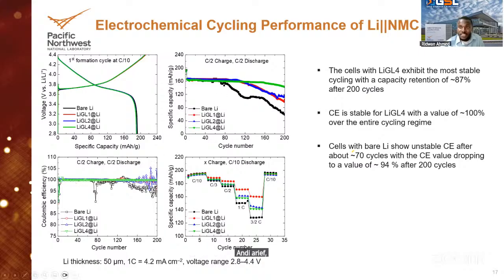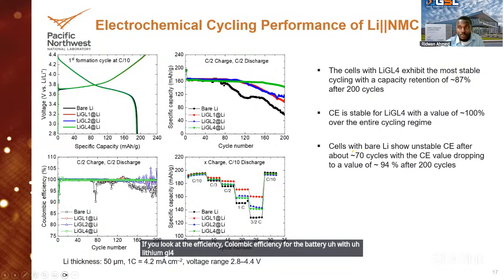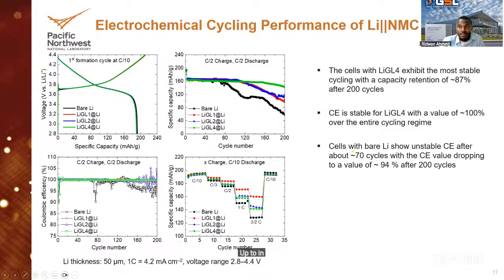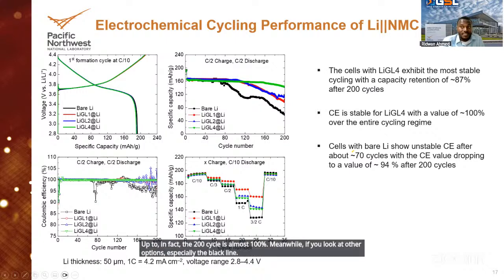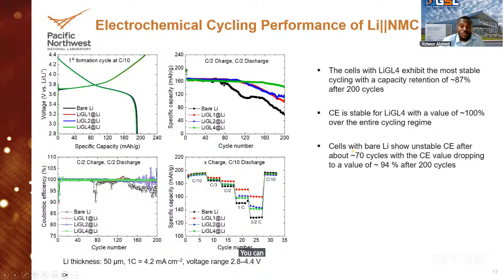And if you look at the Coulombic efficiency for the battery with LiGL4, it's pretty stable, up to 200 cycles it's almost 100%. Meanwhile, if you look at other options, especially the black line, where nothing is done to the lithium, we can see that the efficiency is dropping so fast.